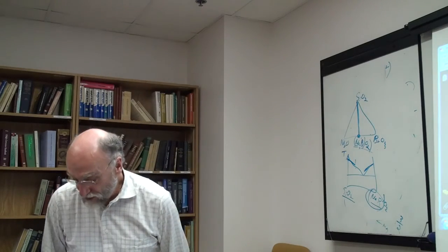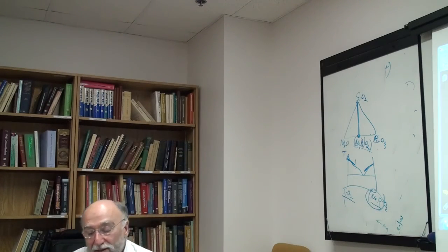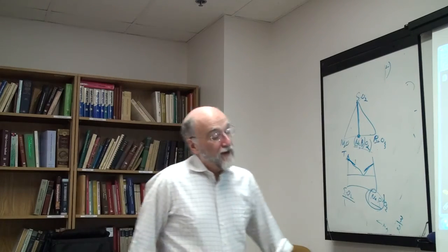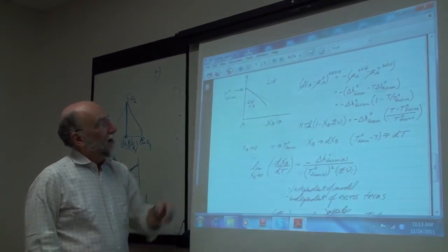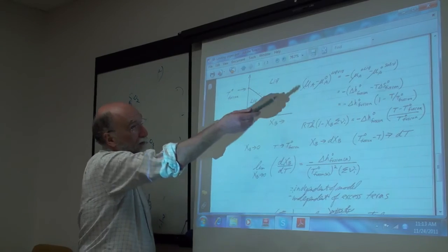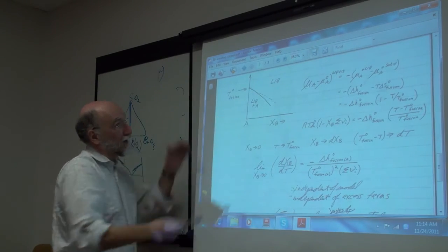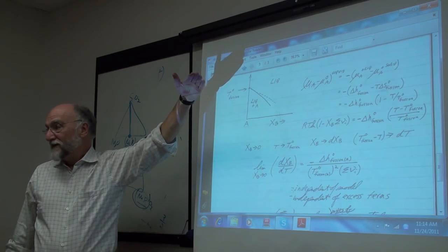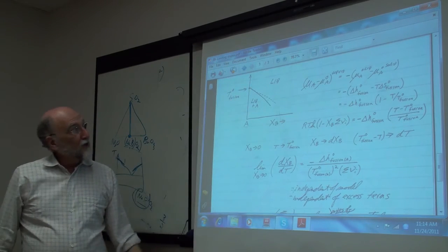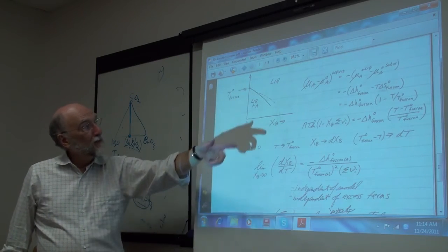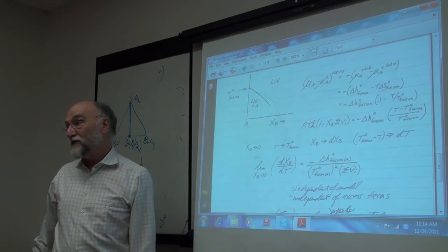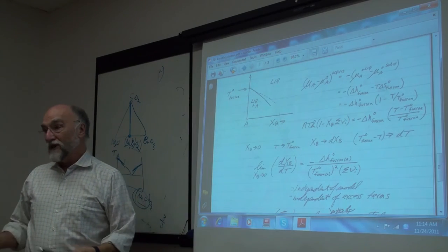So this one particle slope thing can be a very useful concept, and I showed you before, if I know the number of foreign particles is one, for sure, and then I find that I don't obey the limiting slope equation, well then it's probably because I have solid solubility, which will always raise the liquidus. Or I even showed you the other one, when you have a very high temperature fusion, you're sure about the number of particles and you're sure there's no solid solubility, well then the limiting slope will let you calculate the heat of fusion. So this is a really useful equation.